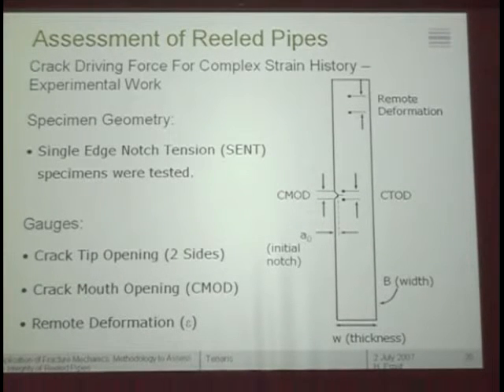But what we did is use the very commonly used single-edge notch tension specimens that are recommended by the standards to do this type of thing. The reason to do that is because it simulates, or supposedly simulates, the constraint. There was some question there before regarding the constraint. It is believed that the single-edge notch tension specimen simulates the Q factor, if you want to use a two-factor fracture mechanics approach. It simulates pretty decently the behavior of the pipe, the pipe in bending.